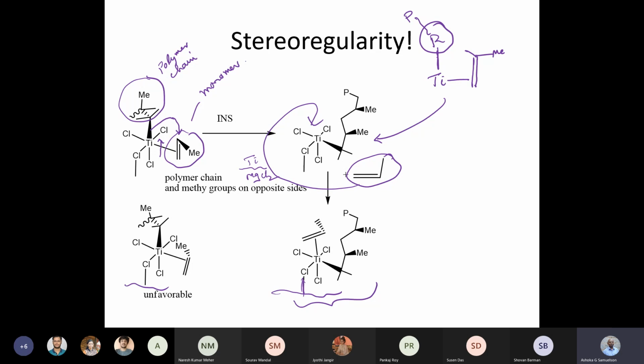So if I bring the methyl in a fashion that brings the methyl group towards the large alkyl chain, that would be unfavorable. The best way to do it is to orient the methyl always away from the polymer chain. Since it's always away, you always end up with the methyl group on one side of the growing polymer chain. And that is why you have isotactic polymerization.